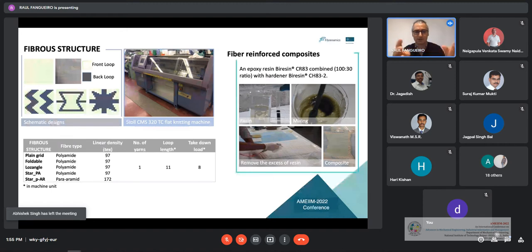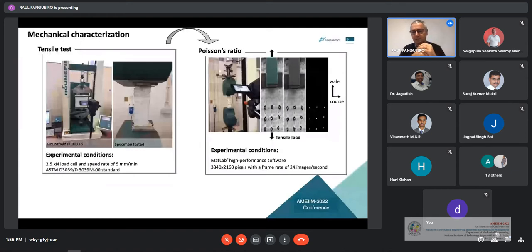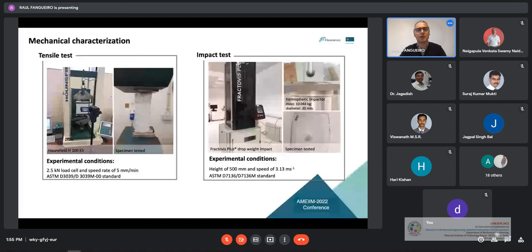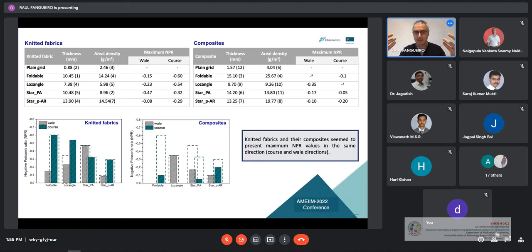So we have at the university textile equipment that can help us build the structure in order to have this auxetic behavior. Then we can impregnate with a matrix, of course, and use image analysis to understand exactly if we have or not this negative Poisson ratio in the material, and to characterize all the samples based on these fibrous arrangements impregnated with epoxy matrix. The tricky thing is to convert this auxetic behavior we normally have in a fiber-based structure, when impregnating this fiber structure with a hard polymeric material like an epoxy matrix, and to transfer this auxetic behavior to the final composite we get.